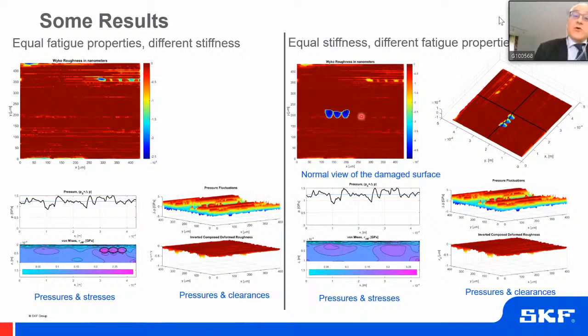But now we introduce lower fatigue properties in the area where we have the inclusions. And then you generate the failure immediately here. You can see the failure. And this is typically what you will need to do if you want to model, for instance, the remelting of material coming from an electrical discharge in the contact. Once you generate a crater from electrical discharge, you basically remelt the material and you soften it. And it will have the same stiffness, but it will have much lower fatigue properties than the rest. So it's interesting just for the record.